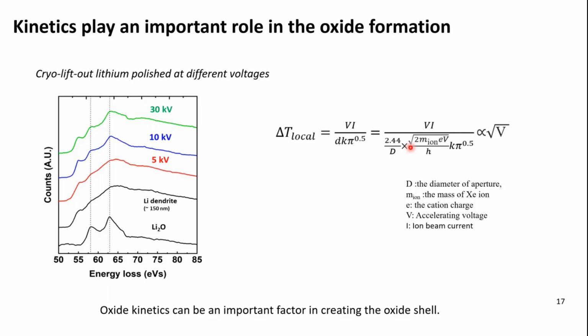So the thermodynamics always wants to form lithium oxide in the cryo-FIB chamber, and if you have a certain threshold temperature, kinetics can be accelerated, and ion beam accelerating voltage plays an important role. And this data also suggests that the oxidation takes place in the FIB chamber instead of the samples being stored in liquid nitrogen.